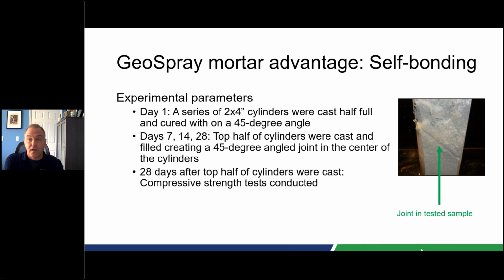So to show an example of that, we did a test with some 2-inch by 4-inch cylinders where we cast the bottom half of the cylinder on day 0 at a 45-degree angle. We then cast, at various different times, the second half of that cylinder on the top with no other preparation than just dampening of the material. And then we tested everything after the top half of the cylinder had